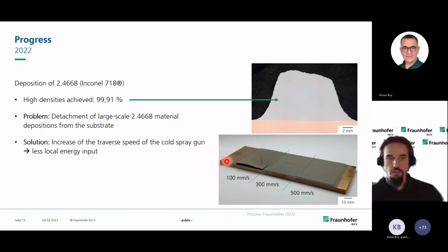And the solution was very simple actually, but nevertheless, it took quite a time to get through it. It was just increasing the traverse speed of the robot, which was guiding the cold spray gun. So we achieved a less local energy input. And by that, we managed to get a good bonding of the sprayed material to the substrate.